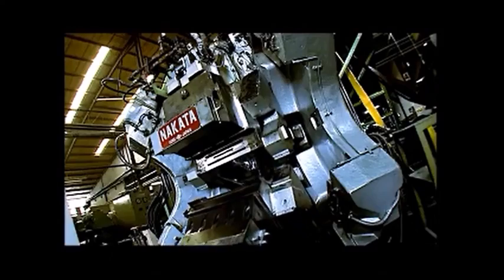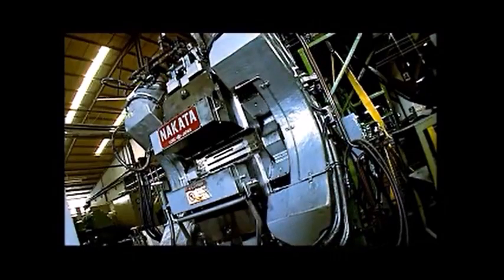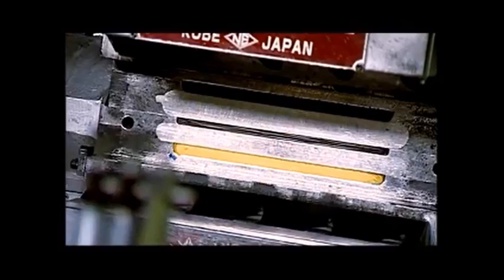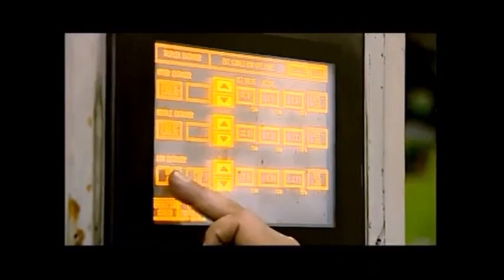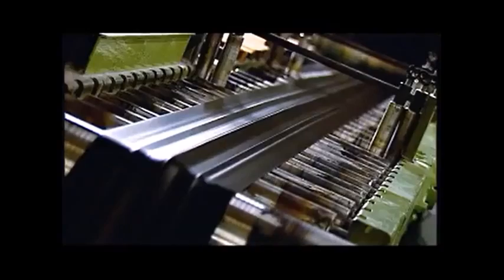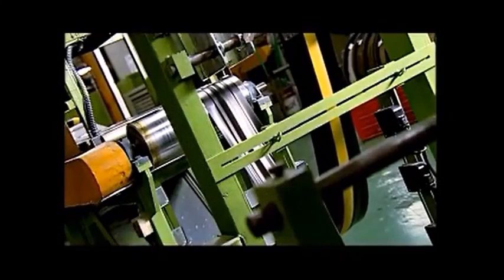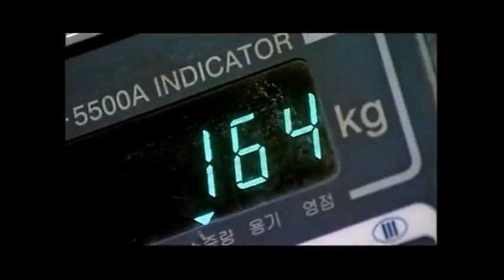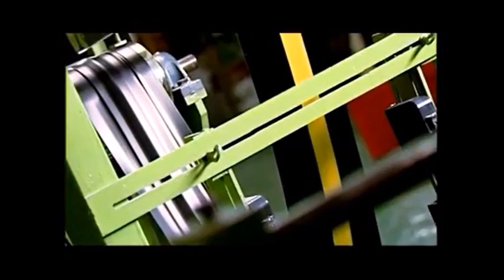The extruder combines different rubber mixtures under enormous pressure. A triplex extruder can combine 3 rubber mixtures, for example, center tread, shoulders, and sidewalls. A unique endless strip is produced for each kind of tire, cooled, checked for regular weight, and laid up in rolls.